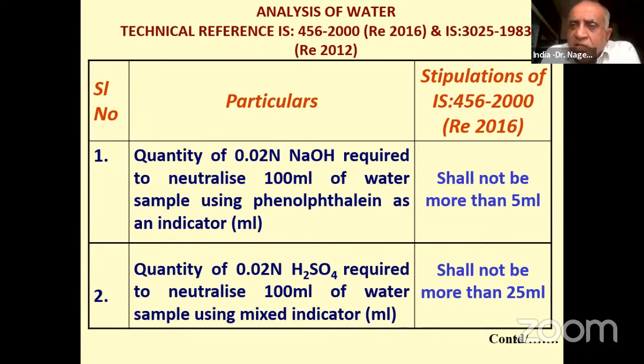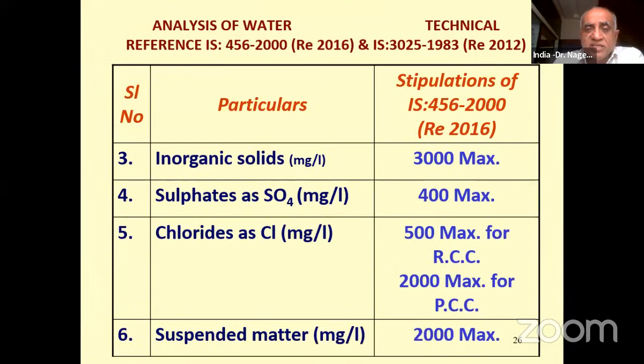So this is a requirement. When you do the titration of the water using this procedure, the titration value shall not be more than 5 ml. Similarly, for the acidity test, the quantity of 0.02 normal sulfuric acid, H2SO4, required to neutralize 100 ml of water sample using a mixed indicator shall not be more than 25 ml. So this particular parameter many times doesn't conform. If you take a sample from the borewell, many times this may not conform. So like this, alkalinity test and acidity test are important.